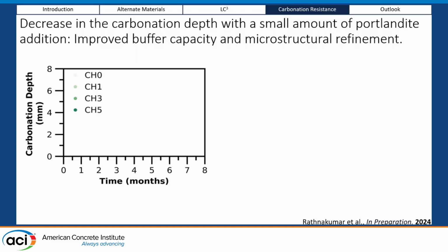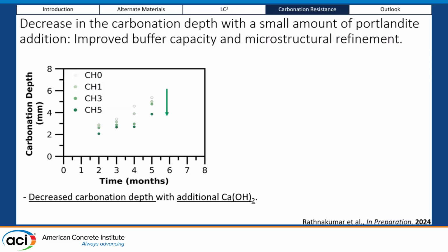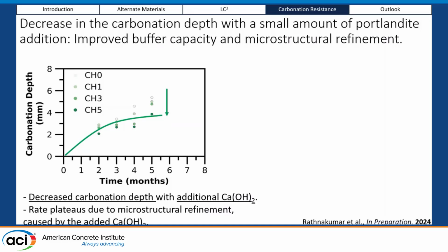With new sets of blends with 1, 3, and 5% portlandite addition, we definitely see a decrease in the depth of carbonation. This is natural carbonation data. We see a decrease in the depth of carbonation with time. We also see a plateauing of the depth values with time. So we hypothesized that this decrease in depth and the plateauing of the depth data is caused by the refinement of the microstructure, which inhibits the ingress of CO2.